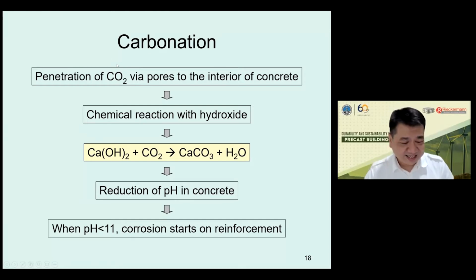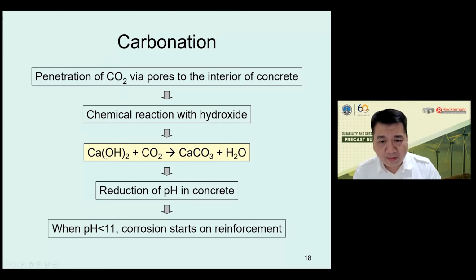And when carbon dioxide penetrates into the concrete, it will react with the calcium hydroxide, producing calcium carbonate and water. With the reduction of the calcium hydroxide content, the pH in the concrete will reduce. And when the pH is less than 11, the corrosion will start on the reinforcement. So this is the basis of carbonation.